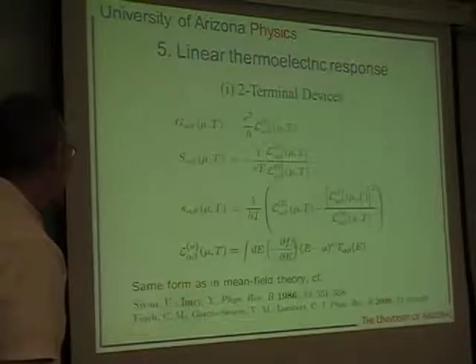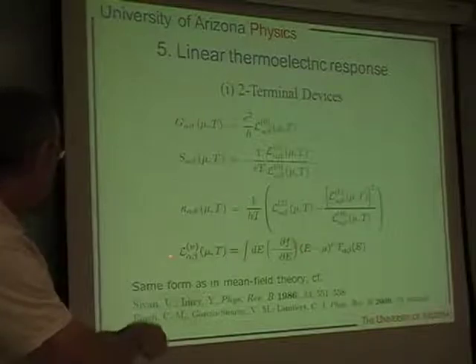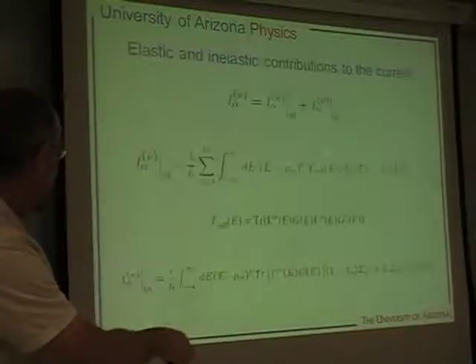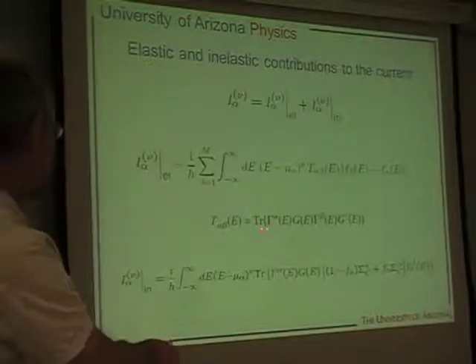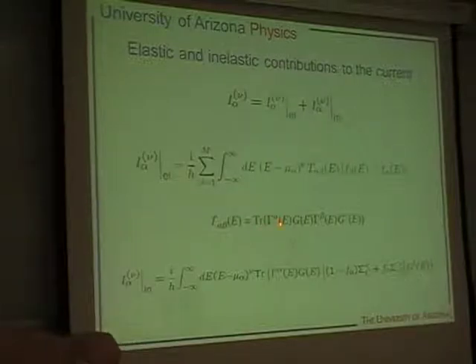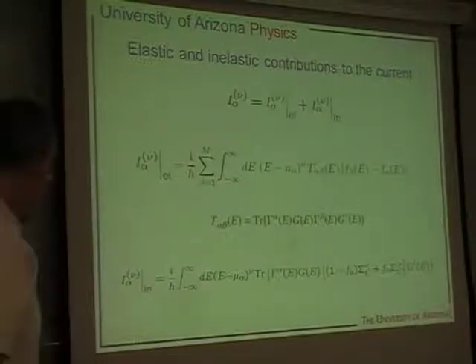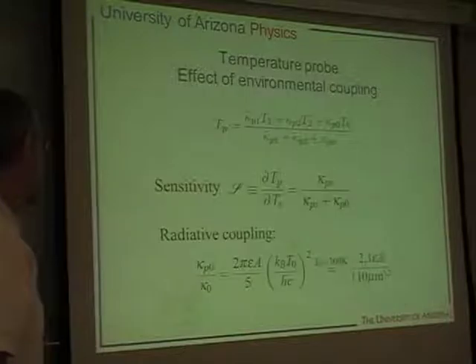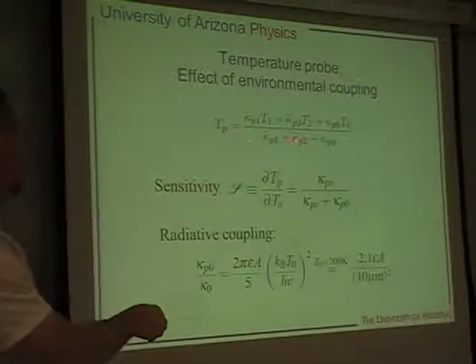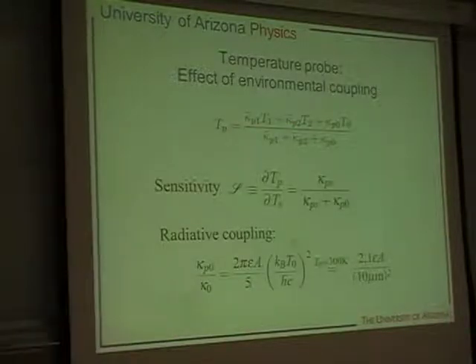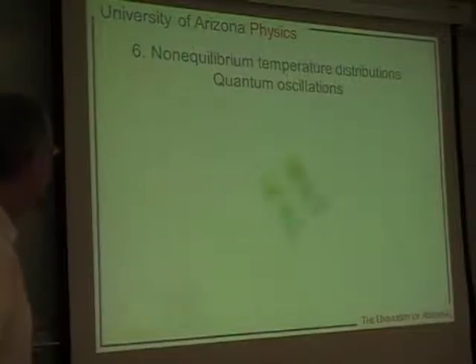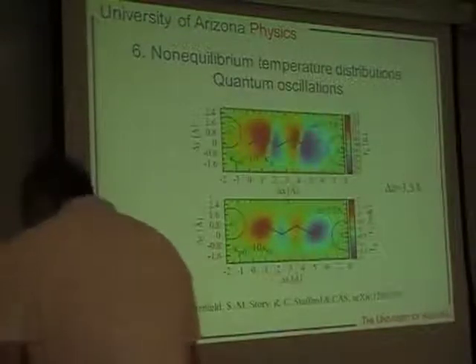I just wanted to show. You see, here is how those guys depend on transmission. Here is how transmission depends on the coupling. So if you make this coupling very small, it's the same thing that appears in both the numerator and the denominator. So essentially, the measured temperature does not depend very strongly at all on the strength or the nature of the tip sample coupling. Of course, the resolution, I don't want to go through the whole thing again. Let's just skip.